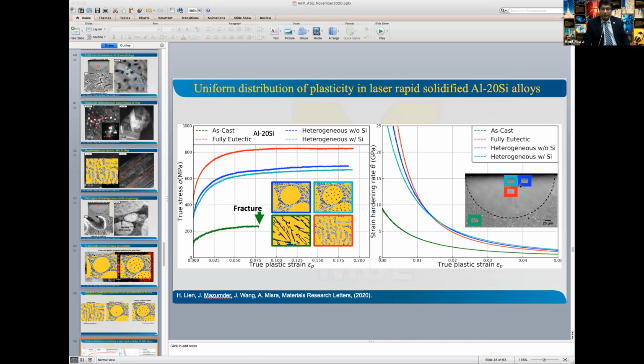And near the surface, you'll see more of the hierarchical structure with the aluminum dendrites. When we get those silicon precipitates, it's still not known. I think there's a lot more work to be done to relate the structure to the property, but also relate the structure to the processing. Because we can't measure the cooling rate, they are doing calculations of the cooling rate in the melt pool. So there's a lot more work to be done there.